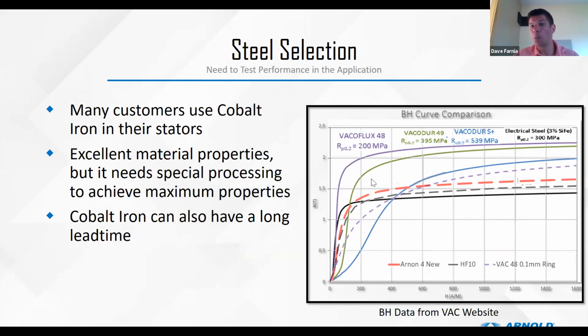When we get stators that are cobalt iron, it's working with the lamination vendors that are going to do the stress relief annealing. They're going to be very careful about the stacks that they send, and then validate the performance of the finished lamination, not just say, well, the incoming material for cobalt iron has this behavior, it's in spec, we're going to stamp it and then ship it. We need that stress relief anneal. If you're working with cobalt iron, at that point it's experience. What is the material that you've gotten in and how does it compare to your predicted results, and then calibrate your model based on that data.